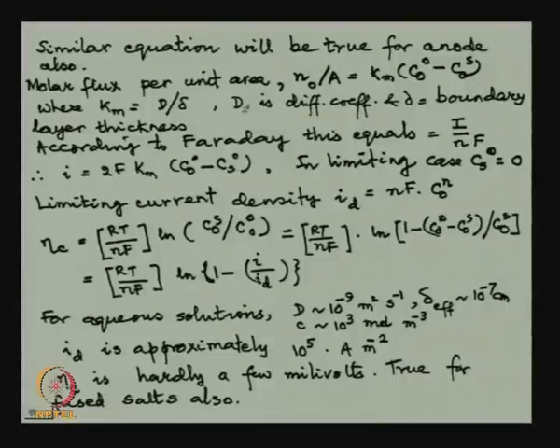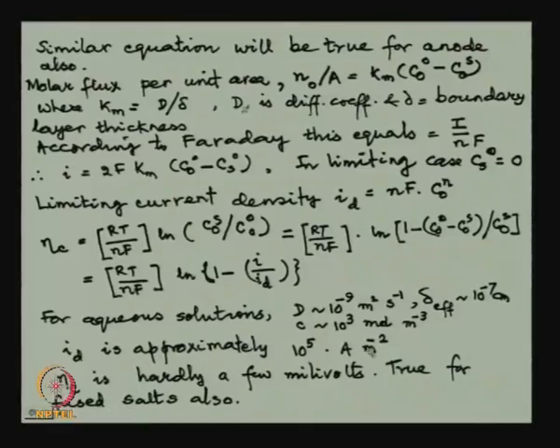That because there is an overpotential, that does not mean that we need to apply a lot more voltage now. That is not required, because the overpotential is only a few millivolts, whereas in most cases you will need several volts for electrolysis. But what is important is that there is a limiting current density, and in most operations you will not be able to pass more than 10 to the power 5 amperes per meter square.